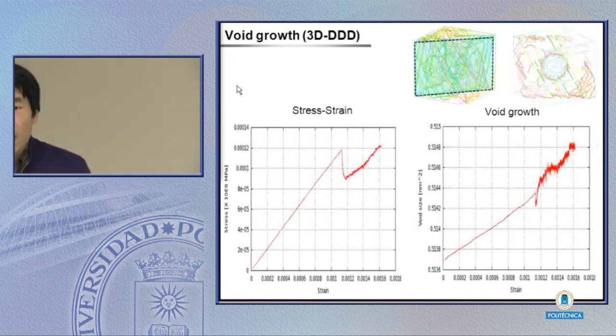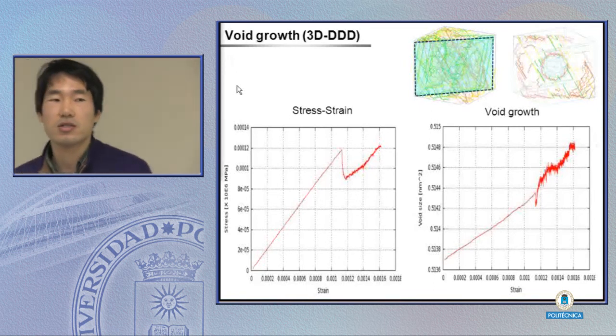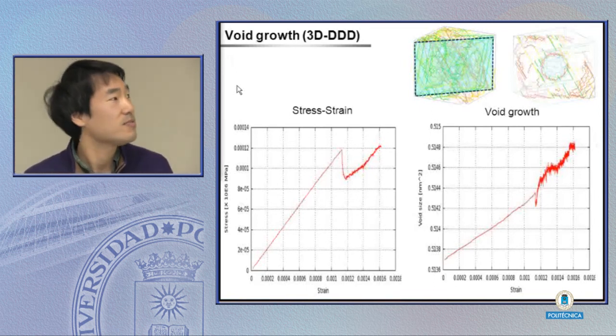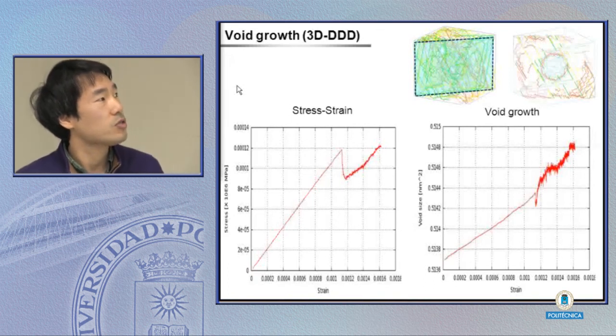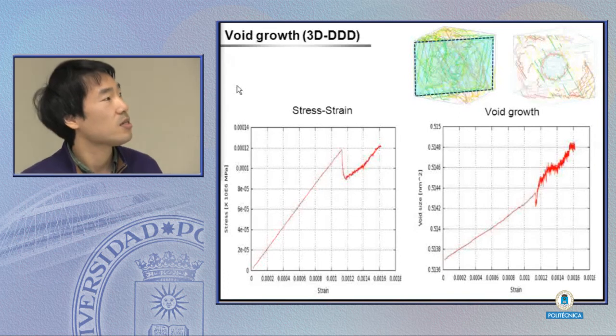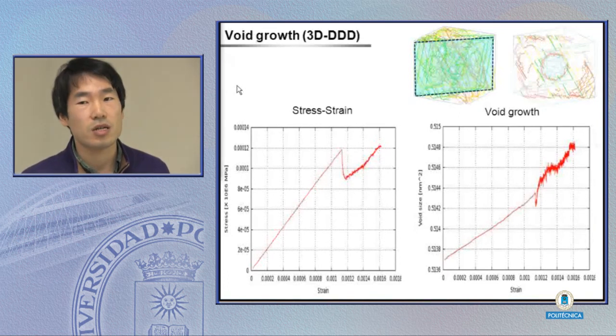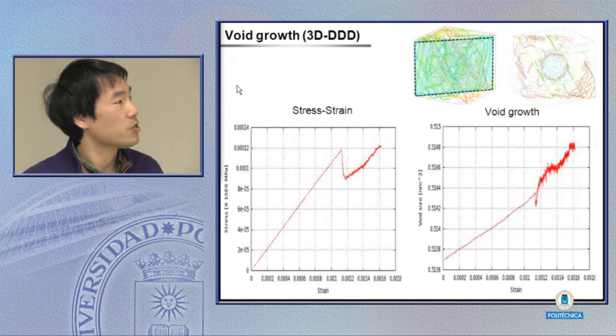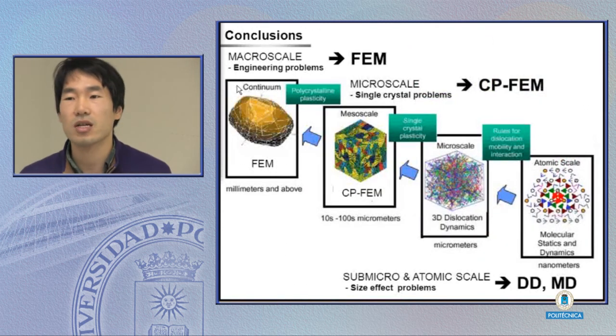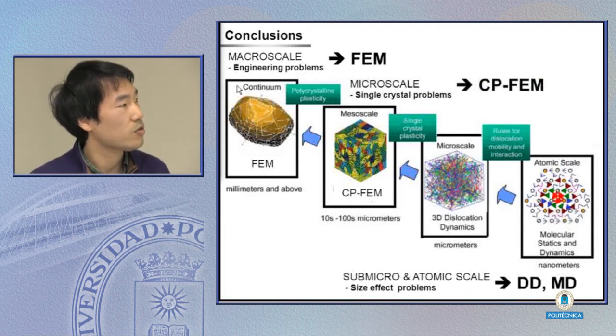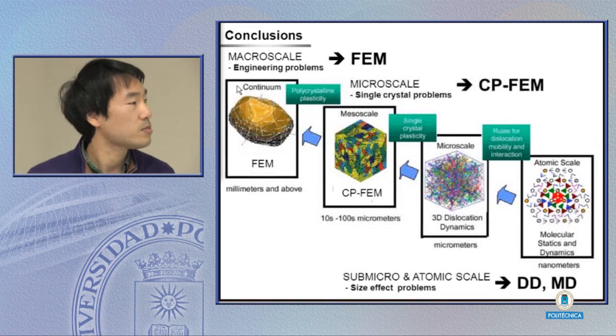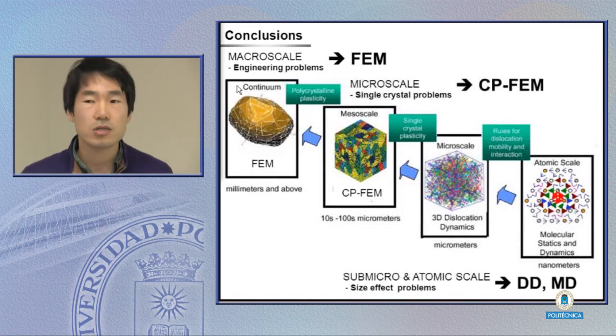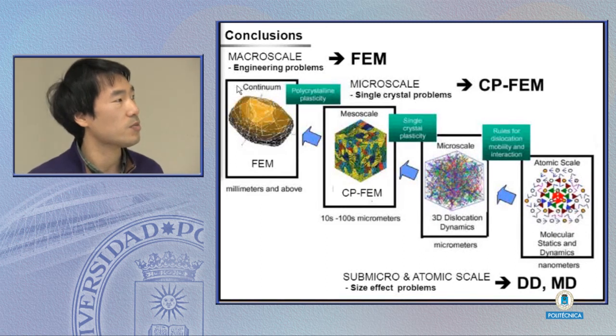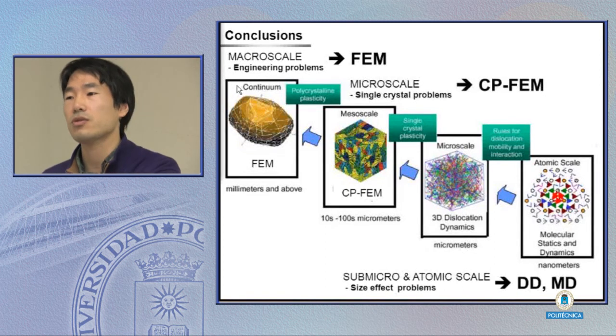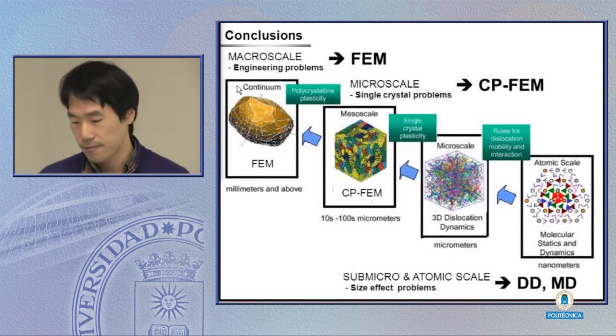And I usually show you the result of this morning. Here is the result of this morning. I do the same procedure with the void growth, like the molecular dynamics, using dislocation dynamics. And this gives the stress-strain curves and the void growth, just like the molecular dynamics. For future work, I will do the same procedure with different sizes, like the molecular dynamics, and then we can plot the void growth with the sizes, and compare it with the molecular dynamics and experiment like this.